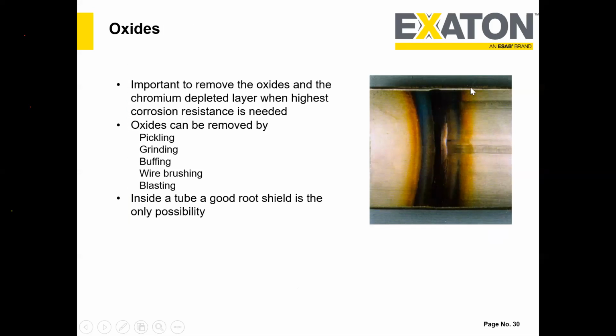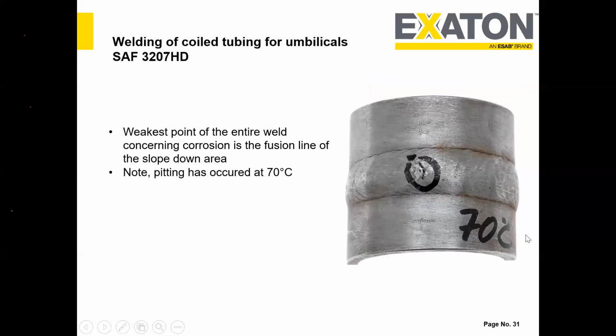Oxides are absolutely undesired because the higher the oxide content, the lower the corrosion resistance. So please remove the oxide layers. It could be either pickling and passivation, which is the best thing. I'll explain later, also we have a chart. Other methods are grinding, buffing, wire brushing, or blasting. Inside the tube, good root shielding is basically desired.